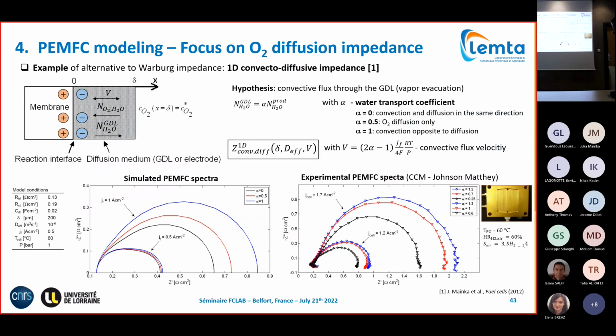As well, within our group, we found improvements of the diffusion impedance. Just to give you an example of what we did, we developed a transport impedance that takes into account convection in addition to diffusion, by introducing a convection velocity depending on a water transfer coefficient. If this water transfer coefficient is 0.5, you have diffusion only. If it's 0, you have convection in the same direction as diffusion.